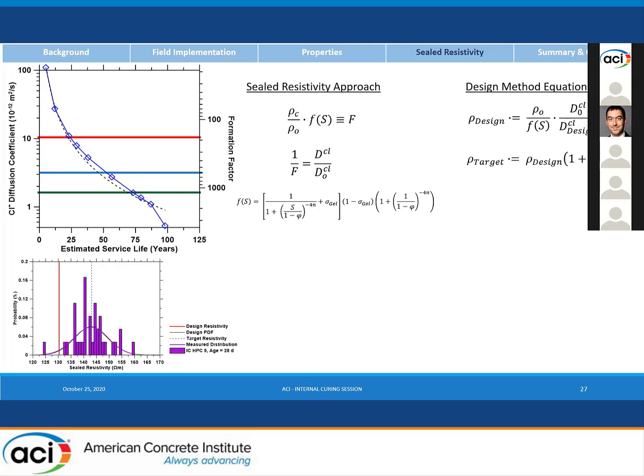And so we did this for one of the bridge decks, the fifth bridge deck. So this is an estimation made at a specific date, 28 days, and we can see that for this kind of cooked up example, we've hit a target value here within the specified distribution, and it equals, I think, about 50-year service life at 28 days.